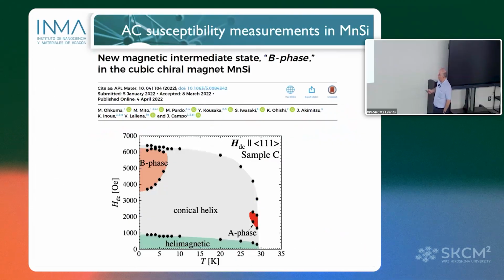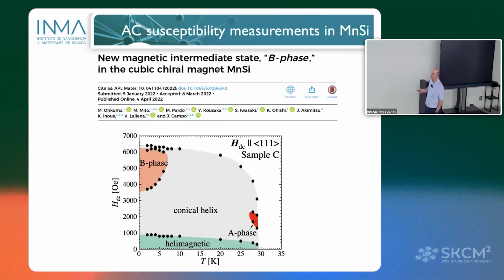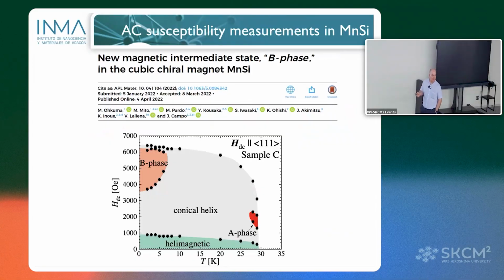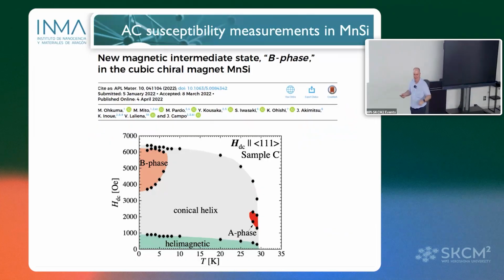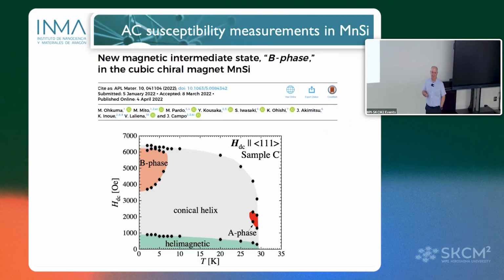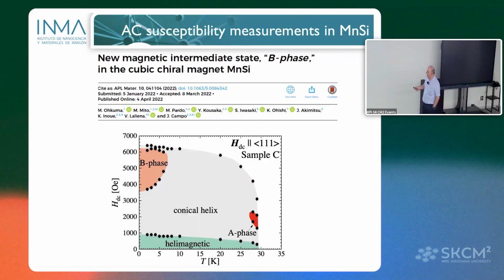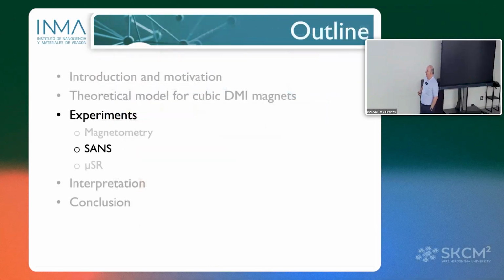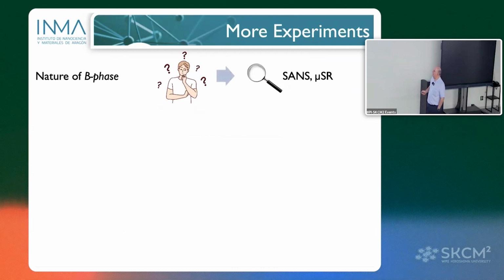Considering all this data, we found something here. This is what we call the B phase. Then the theory brings us to study this B phase. What is the origin of this B phase? Why do we have this anomaly only in the 111 direction, when the magnetic field is applied along 111? Skyrmions are observed in all the directions, but not this. And we are people expert in large-scale facility techniques, and we did SANS and muon spin rotation.